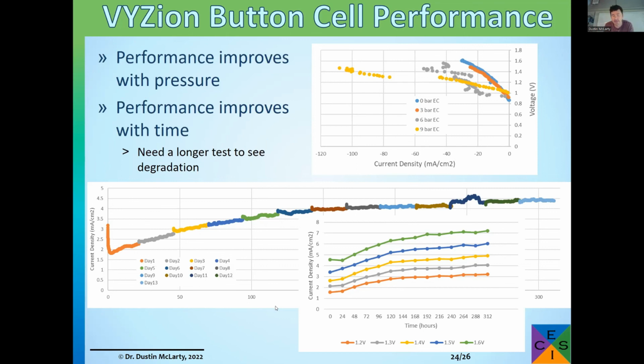So it likely had issues with the original porosity, but it does seem to be perfectly reversible. We've cycled it back and forth a dozen or 20 times and seen minimal degradation with the cycling. We do know the oxidation state is changing. We can observe that just with the color change, but it does seem to be a reversibility that is not causing a degradation.